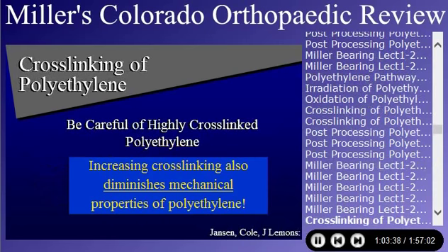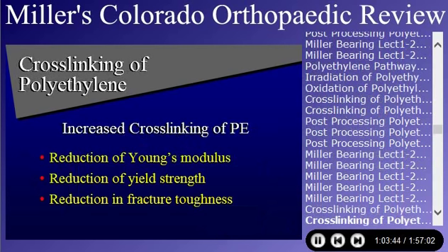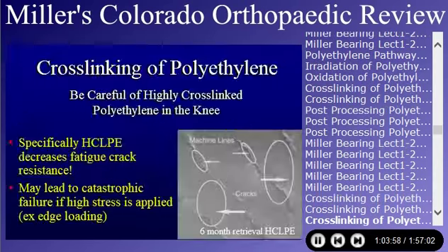Increasing the cross-linking also diminishes the mechanical properties of the polyethylene, and you've got to be really careful how you use it. In the hip, it's good because you're loading in compression mainly, but in terms of the knee, it may not be the best thing. Remember that highly cross-linked polyethylene reduces Young's modulus, it reduces the yield strength, and it reduces the fracture toughness. And specifically, it decreases the fatigue crack resistance, and it may lead to catastrophic failure if high stresses are applied, i.e. if you have edge loading in a total knee. So I think of high cross-linked polyethylene as being brittle, more like a ceramic. If it's more like a ceramic, it's going to crack more. And that's how I remember high cross-linked polyethylene.